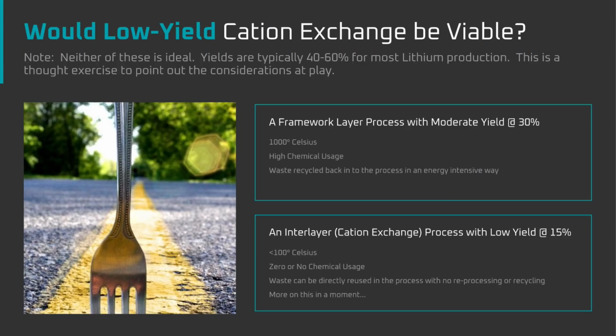I'd be curious to know what the extraction percentage would be with just heat, salt, water, and no acid. Even if the extraction percentage is relatively low, the process would be extremely low energy compared to a roasting process and could be lower cost despite the lower extraction rates. That is, heating water to boiling and extracting 15% of the lithium would be better than roasting the clay to 1000 Celsius and extracting 30% of the lithium.